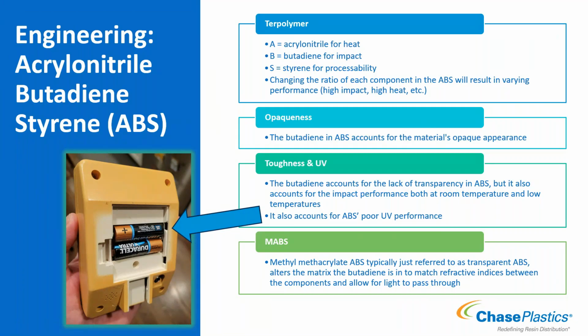What happens is they change the matrix. So instead of just a SAN matrix, styrene acrylonitrile matrix, they also add in methyl methacrylate. So the matrix the butadiene is in changes its refractive index, and now the two match, so it allows light through. A really complicated way to just say we can make ABS transparent - we just alter the matrix the butadiene is in.